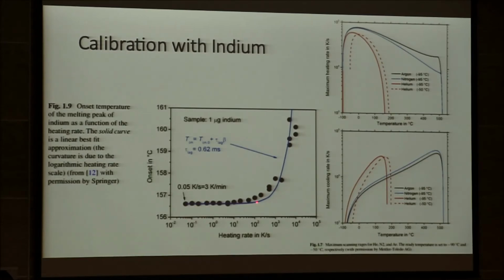We know where it stops working. We've changed the heating rate here. And we can see that beyond a certain value of heating rate, the value of what we're trying to measure runs away. That means we're losing it. The machine no longer has it completely under control, but you can see where that happens. So we can really drive right up to the edge of the precipice and play there as long as we want. And we know if we fall off. Okay? And you can see here the onset in temperature. So this is 157. This is 160 degrees. Only 3 degrees. This is a calibration using indium metal, which we use for the device.